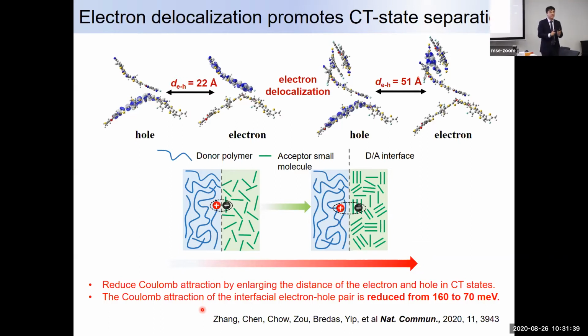But of course, in the real case, I think it will have even more aggregation of that. So if this can go down to the room temperature, which means, right, even at room temperature, we already have enough energy to separate the exciton. That also explains why, right, we don't need to have any energy offset for the exciton dissociation. The material aggregation already create a loosely bound charge transfer exciton. Okay, so this is one of the reasons why this type of new material, they are very interesting molecular structure, bringing to an interesting electronic structure, and then eventually they're favorable for exciton dissociation.